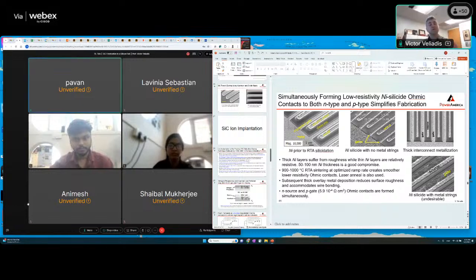Okay. And that's very important because in a planar device, and even in a trench device, when you try to reduce the length of the channel to minimize the channel resistance, the device basically does not hold well when it comes to short circuit events. So you're compromising short circuit performance with lower resistance by making the channel thinner. You don't have to make that compromise in 10 kV devices because, again, the resistance of the channel is negligible compared to the resistance of that thick drift layer.